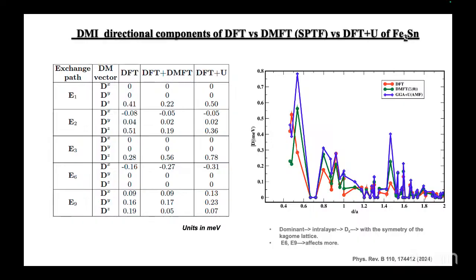If we are introducing strain or doping in the system, I expect that my DMI will change. Yeah, but anisotropy will also change, maybe grow, and then it will hide complex magnetic structures probably here. Because as far as I understand, you don't see any non-trivial, non-collinear spin structure in this particular material without any perturbations like strain or something. Yeah, but the experimental people have reported the presence of magnetic vortices. So we believe that if we are able to account for all the defects, because we haven't taken into account that realistically the system has some kind of vacancy or something like that, we expect some kind of structures similar to what is being reported in the experimental magnetograph experiments. I see. So this is the kind of speculation that we can draw from this.